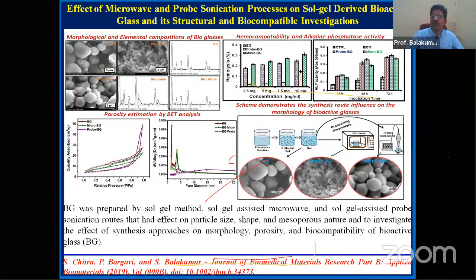Similarly, we also use different sonication or annealing processes, which give different morphologies. When the morphologies are different, the surface area is different. The normal method gives you 20 meter square per gram, but when you use microwave annealing, it changes the surface area. When you introduce probe sonication, there is a break in the particle size, and that changes the surface area and porosity increases. That certainly increases the property, and those materials are good for hemostat application. So that is one of the works.